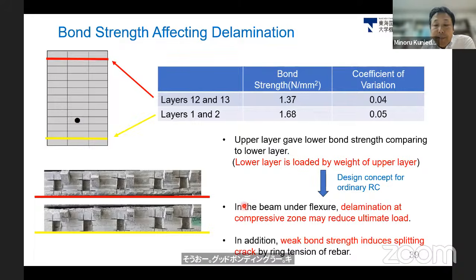And in beams under flexure, delamination at the compression zone may reduce the ultimate load, and we can imagine that. In addition, weak bond strength induces a splitting crack by ring tension of the rebar, around the rebar. So we should improve the interlayer properties when we use them as structural members.